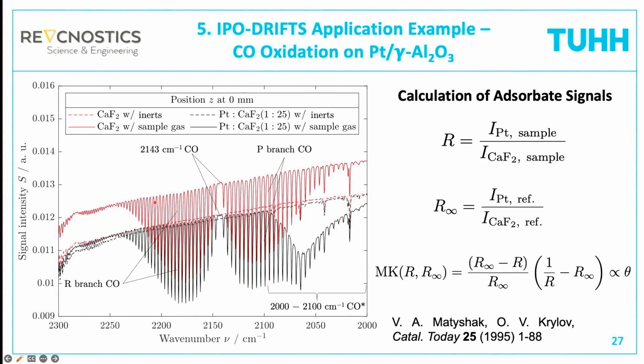So here are the measurements on pure calcium fluoride, the red spectra, which is white. Yeah, as a powder, it's white. And then you see here, this is the platinum catalyst diluted, of course, but it darkens the material, so it becomes grayish. And you see that the overall signal intensity is a bit lower, but when you calculate the reflectivities, this cancels out. And the good thing is you have to use very little catalyst. So even a black material, it's so highly diluted, it will reduce the signal intensity, but you can still measure it. Okay.